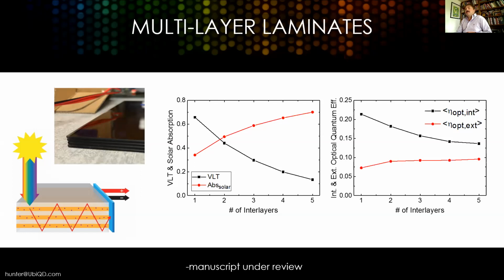A solution to that problem is to make multiple interlayers. We looked at that in the same paper that I just mentioned under review now. We made up to 5 interlayers stacked on top of each other, and you can see that the VLT, the light transmission, does drop, and we can tune it over the range that architects care about. At the same time, the absorption of the device goes up, so the performance should also go up. And we do see that, but it's nonlinear. The internal quantum efficiency actually drops as you keep adding interlayers, due to some effects that we discuss in the manuscript, but you do get an external efficiency improvement. So by adding absorption, you get better performance, but at a nonlinear rate relative to the absorption.